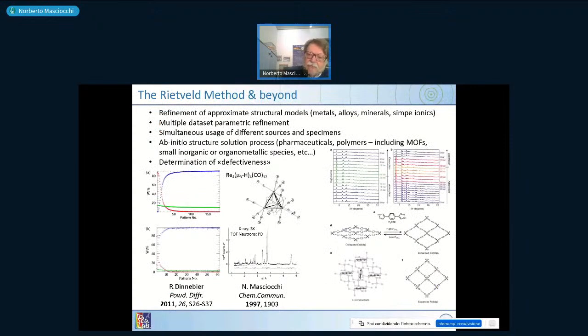So the Rietveld method can give you a lot of information. It has been used to refine approximate structural models from metals, alloys, minerals, and ionic materials. Nowadays, it has also given ab initio structure solution from organic and organometallic material. You can see here a complex organometallic material which has hydrogens. The hydrogen in the presence of a rhenium atom cannot be seen by X-rays, but if you couple simultaneously data from synchrotron, which easily give information on a metal atom, and from neutrons, which give information on hydrogen atoms, by using simultaneously two data sets, one from X-rays and the other from neutrons, you can get the overall picture because the information is encoded partially in the synchrotron data and partially in the time of flight neutron data. So you can have here a multiple dataset refinement.